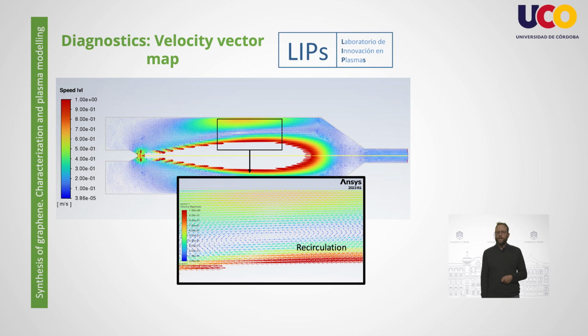If we zoom in on the blue regions close to the walls, we can observe the recirculation process that can be related to a higher residence time and therefore have an impact on the formation and growth of the graphene.